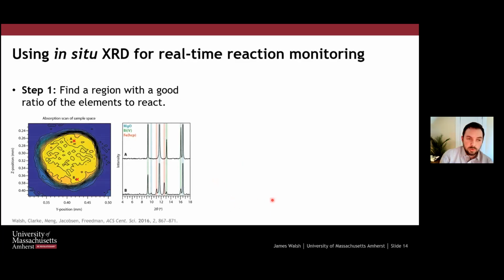So there are a few steps. The first one is that you need to find a place to heat with your laser, a heating spot that has the elements that you're trying to react. And that's not trivial. This is kind of an extreme example, but here we're showing the powder X-ray diffraction between two different sites. So this is just the absorption scan, the transmission scan maybe of the sample space. And what we see is that at this spot, we don't have iron. So these red bars would have peaks if we had iron present, we don't have that, whereas site B does. And so site B is a place that we should go and do the reaction.